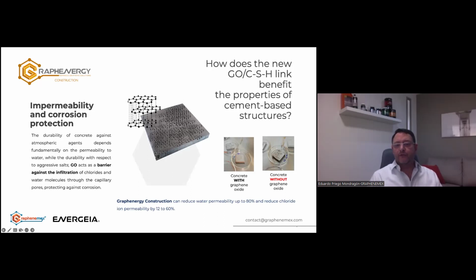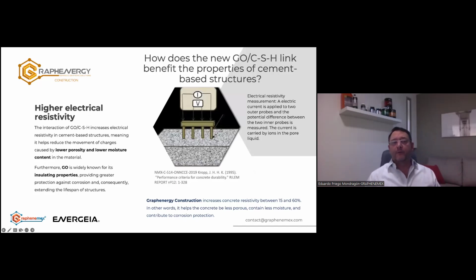Graphene construction shows results that improve water impermeability up to 80% and reduce chloride ion permeability by 12 to 60%. It also provides higher electrical resistivity to concrete. The interaction between graphene oxide and CSH increases electrical resistivity in cement-based structures, meaning it helps to reduce the movements of charges caused by lower porosity and moisture content in the material.